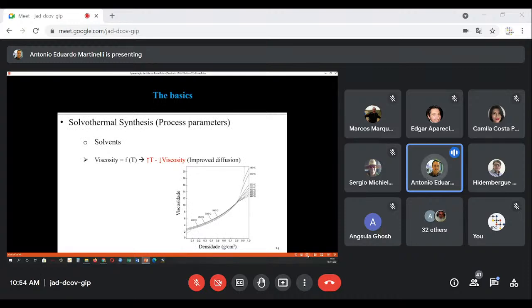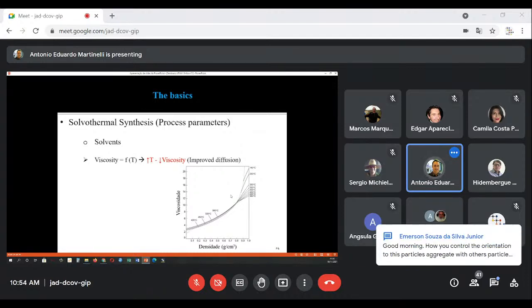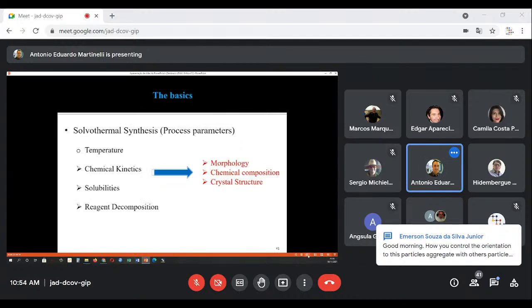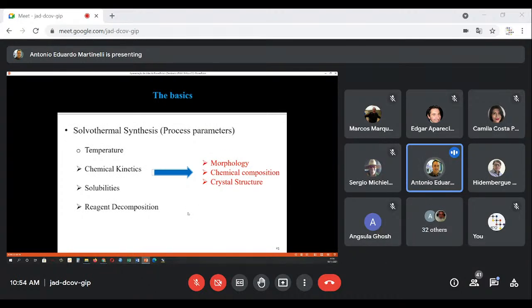As for the solvents, solvents are another factor that must be considered in the effect of solvothermal conditions on solvent viscosity. For water, the viscosity decreases with increasing temperature, which favors diffusive processes. The temperature is a critical parameter because it determines the chemical kinetics and therefore the morphology, the chemical composition, the crystal structure, and also affects solubility and reagent decomposition.